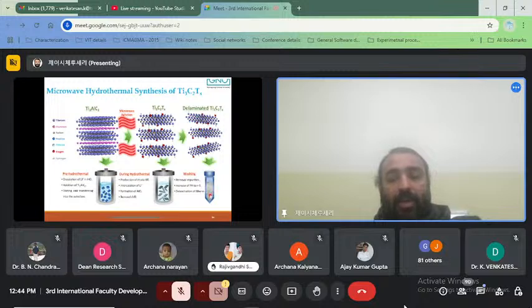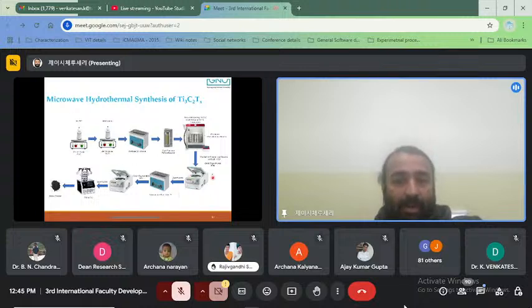Now we got MXene. What we usually do is discard the supernatant part and take the bottom of the material. But if you want very thin layers of MXene, for example 2 layers or less than 5 layers, it is very difficult to get that kind of MXene from the sediment. You want to take the supernatant solution, then freeze dry it, and then you will get the real MXene that is less than 5 layers. That is one of the techniques. Once you freeze dry it, you can store it immediately in a container without undergoing air oxidation. So these are the different steps which I showed.